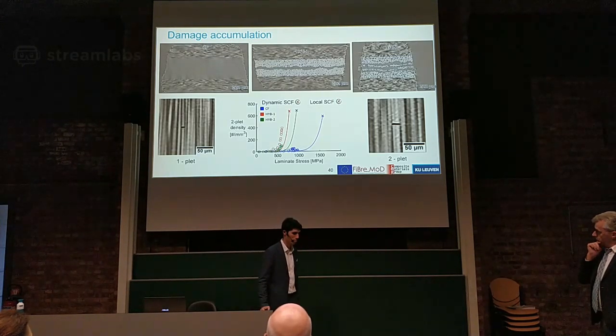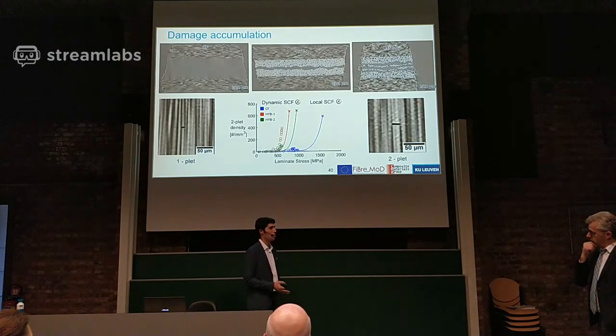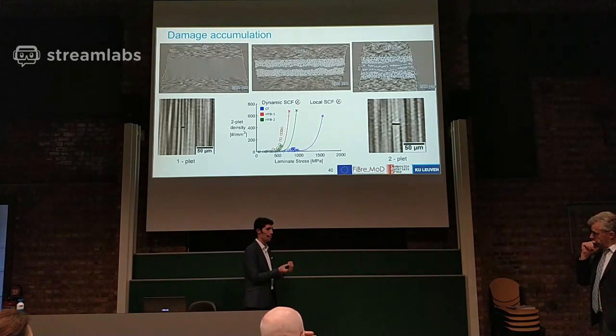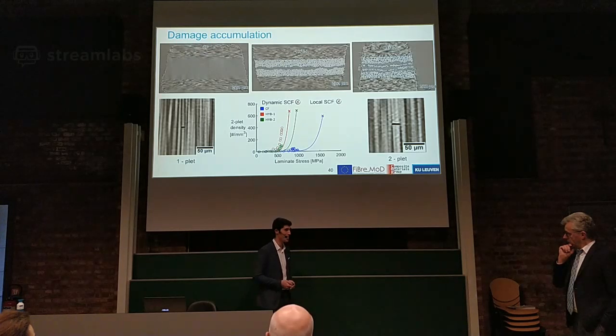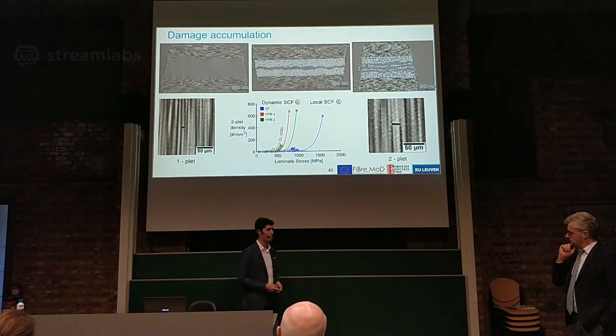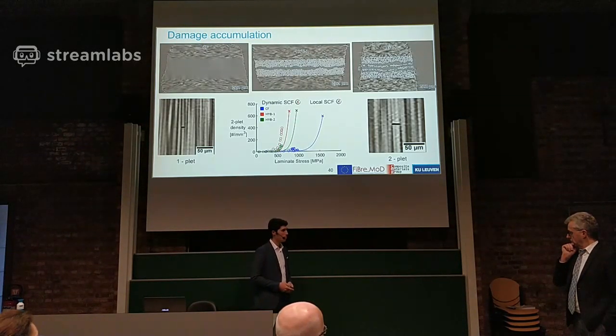I think so, yes. Just by adding local stress concentrations, we've discussed that before. For about a year now, or maybe even just a few months, someone was actually able to measure the intrinsic strength of these carbon fibers. So just by using this value and the local stress concentrations, we can already say, okay, if this fiber in this small region exceeds this value, it will break regardless of having a defect or not. If we still add the defects on top of it and these local stress concentrations, we get the best of both. Now the problem there is computational time, of course. But if there is a way to combine the two things, another layer of scale, then that would be optimal. Concerning the interface?